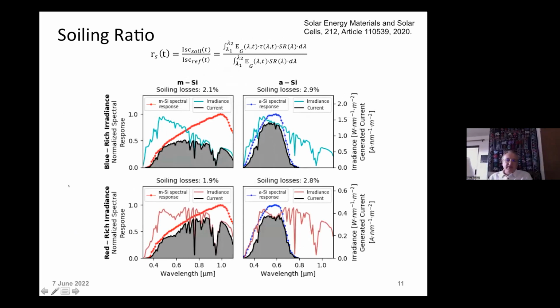So here's a couple of examples of how to think about this in terms of these three quantities: the irradiance, the spectral response and the transmission. These are a little bit busy, but I'll talk you through it. If we have a blue spectrum, maybe it's midday, so the losses through the atmosphere are relatively low. Here in this top one, we have multicrystalline silicon. Here is the irradiance; this shape should be somewhat familiar to you. Here is the spectral response, which is again related to the EQE, the external quantum efficiency. And then we can have a transmission, which gives you the result that you would have a loss, one minus the overall transmission throughout the whole region, that might be 2.1%. So you might lose 2.1% of your power.